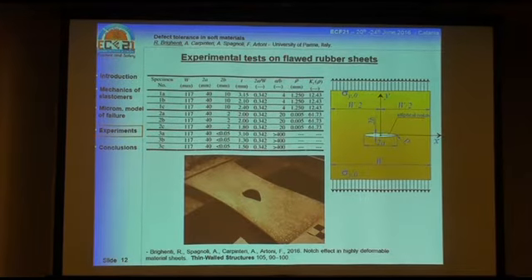To verify our model, we try to test some samples made of very soft polymer, which is called Sylgard. It's a kind of silicone. We consider several plates with different initial defects: blunt, mild notches, and straight crack. We have here the radius of curvature at the notch tip and the stress concentration factor evaluated by using standard formulas.